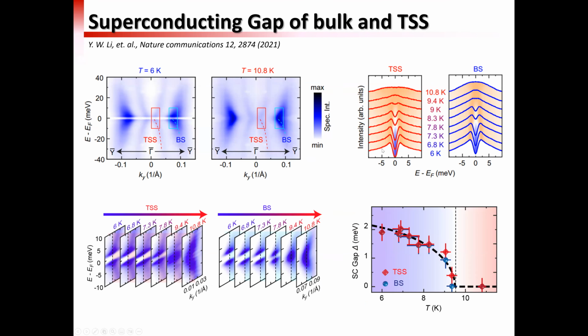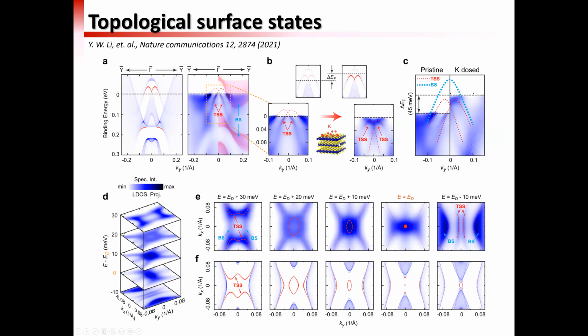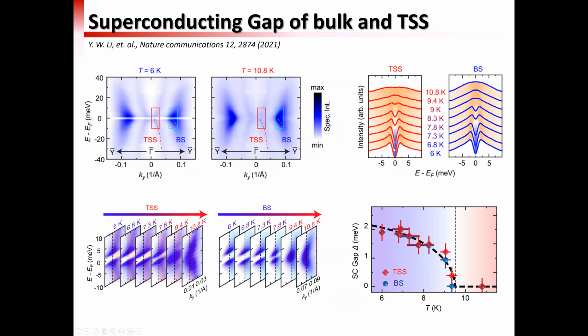The resolution you can see from our spectra. I should have put a raw spectrum here, but you can see from this one. Can you see my cursor? Yes. You can see the quasiparticle peak drop at 0, and one small tick is 2.5 meV. The resolution is smaller than that because you can see the full drop of the spectrum. We actually did a gold measurement that gave about 1.5 to 2 meV. I need to double check, but it's around that range.